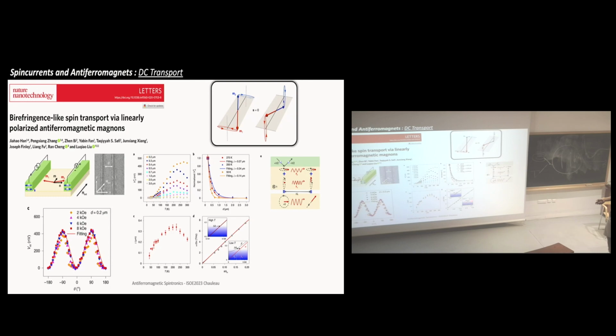What is nice is that at low temperature, those branches are kind of far apart. Then when you go up in temperature, they come closer to each other. This is why you can convey the spin information over longer distances. And they explain the decrease because when you heat up too much, at some point you have too much magnon-phonon scattering, and then you kill the spin information again.